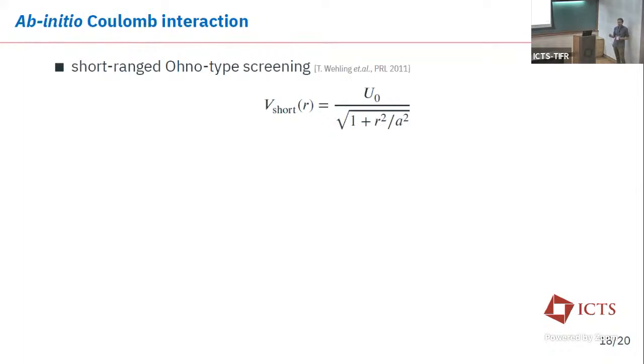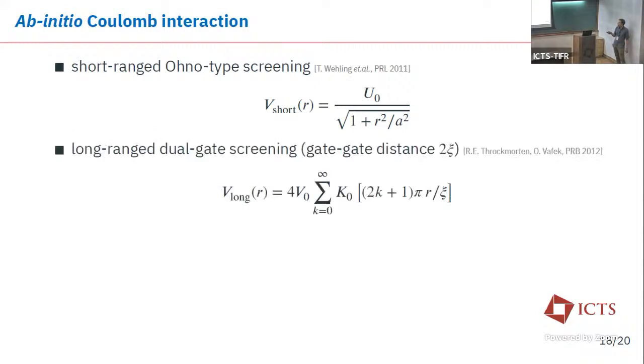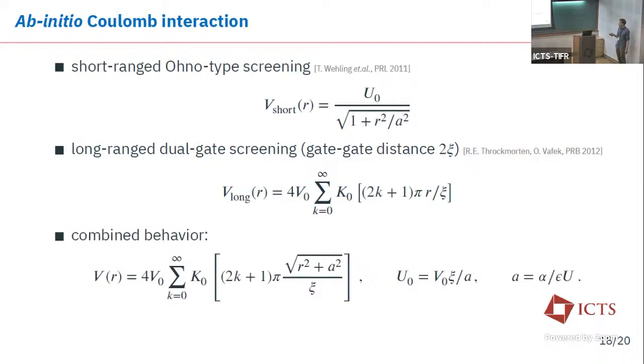We can take an ab initio Coulomb interaction known from 2 sources. The first one would be the short-range screening, which is of Ohno-type. Here you see that you regularize the R = 0 divergence with a kind of square root. The other one would be a long-range dual-gated screening, where you regularize the 1/r tail, or the momentum space Q = 0 divergence, with some exponential written here in terms of Bessel functions of the second kind, I think. The point being that we can combine both of these behaviors to arrive at an interaction that is ab initio motivated, that is both short-range screened and long-range screened.